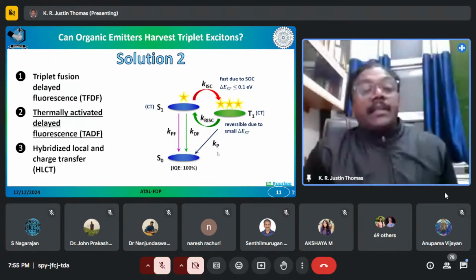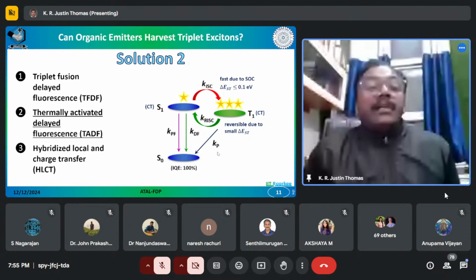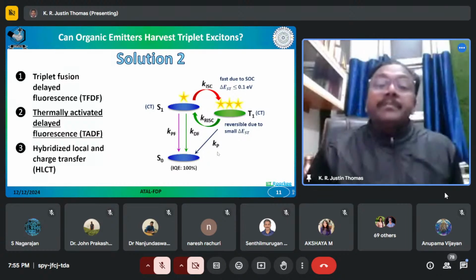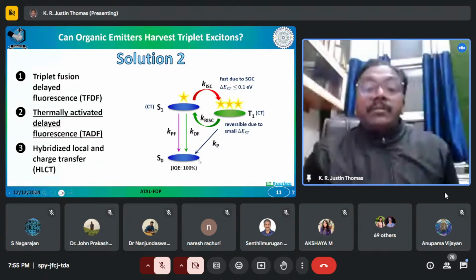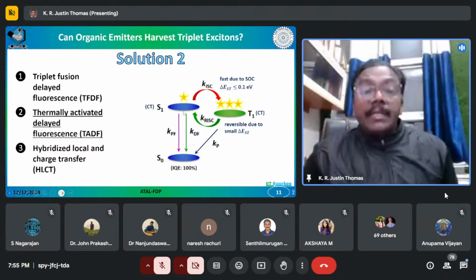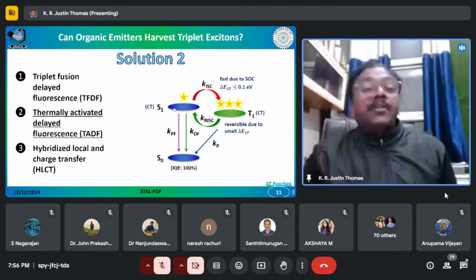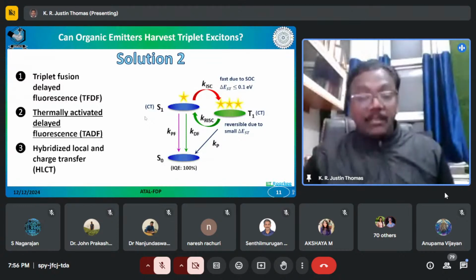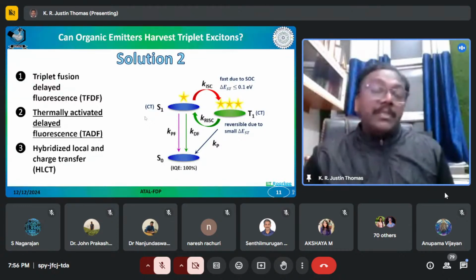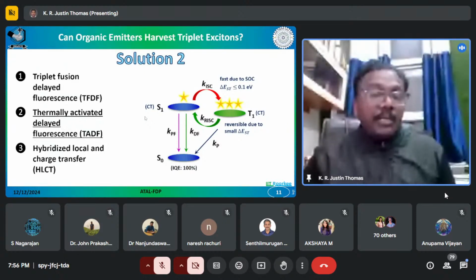Thermally activated delayed fluorescence can also be explained by a Jablonski diagram, as I have shown here. The molecule is excited to the singlet excited state. Here the singlet excited state is charge transfer in nature. That means the molecule should have a donor-acceptor structure. That is an important aspect, because only then can you have a charge transfer from donor to acceptor. So the donor-acceptor structure is an important criterion for realizing TADF. That is the number one criterion.